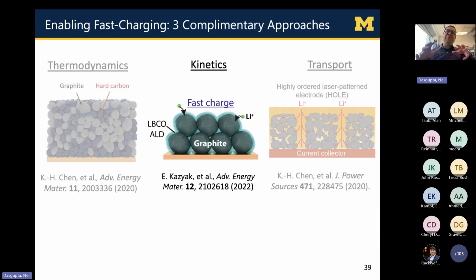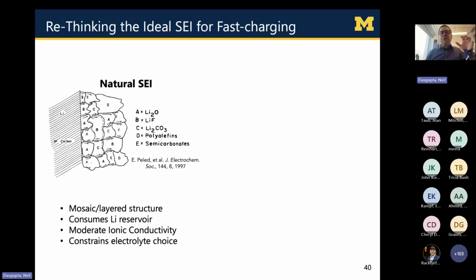So lastly, let me show you the one that was really the most exciting to us, which was thinking about the kinetics of the interface of the anode material. Most people, when they view fast charging limitations in batteries, are heavily focused on transport. They're trying to figure out, how do I get these lithium ions to go in and out very quickly? But there hasn't been nearly as much attention paid to the effect of the interface on the rate limitations of fast charging of batteries. If you go look in the battery literature, the only real reason a lithium-ion battery even works is because there's a magical surface layer that forms on the surface of the graphite during the first formation cycle. We call that the SEI, or solid electrolyte interphase layer.